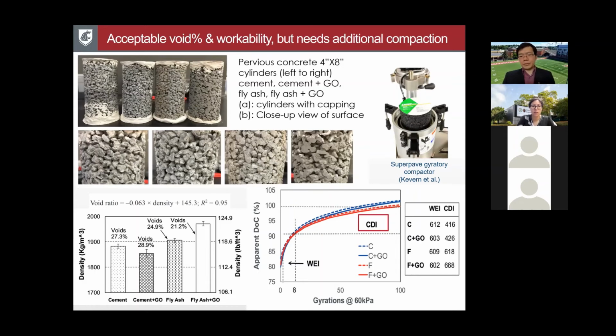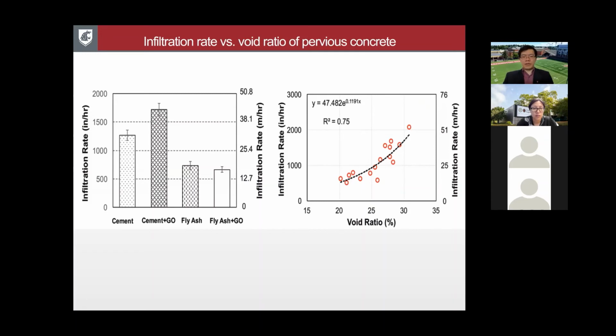they're still highly compactable. Now, infiltration rate versus the void ratio, again, there's a direct correlation. You can see the R-squared 0.75. Now, infiltration rate on the left, you can see even the fly ash one or fly ash with GO pervious concrete has significantly lower infiltration rate, but don't get too concerned about that, because when you look at the infiltration rate, they're still close to 600 inch per hour. You are not dealing with that kind of heavy rain. Well, I'm not sure about Florida, but highly unlikely.